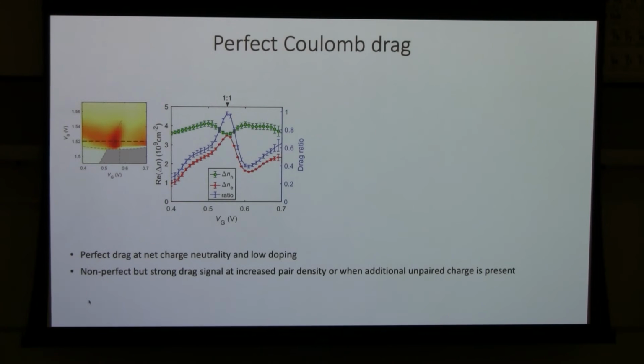So we can do some line cuts to look at it more carefully. For example, if we do a horizontal line cut, that means we change the electron-hole balance. The green curve shows the hole current, and the red curve shows the electron current. The ratio of them reaches almost 1 within experimental uncertainty, at an electron-hole density 1-to-1 ratio. And then if you start to add excess electrons or holes, this drag signal remains significant, but it becomes smaller.